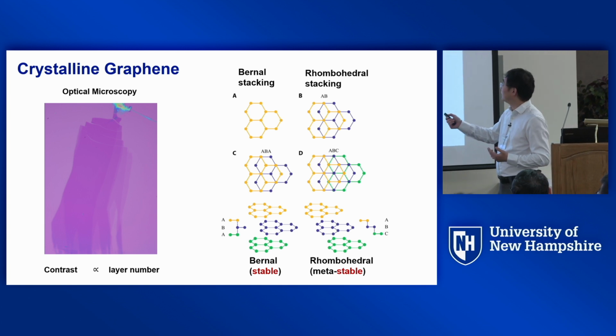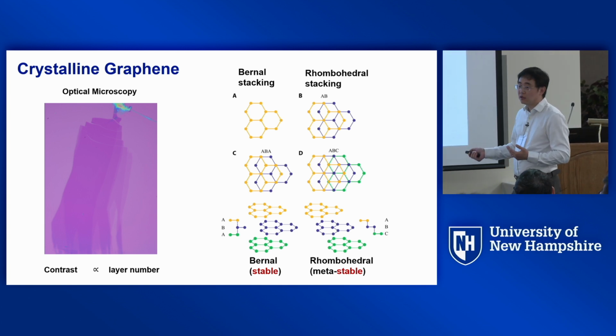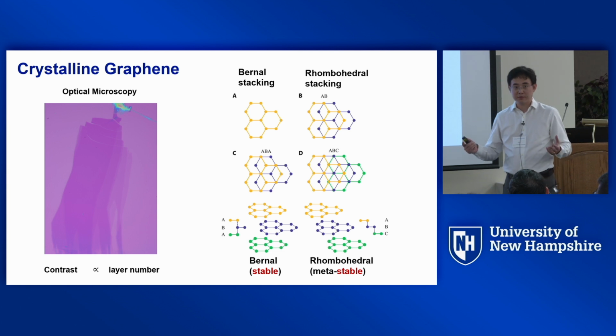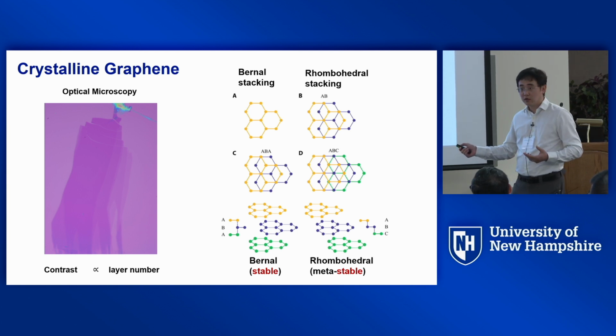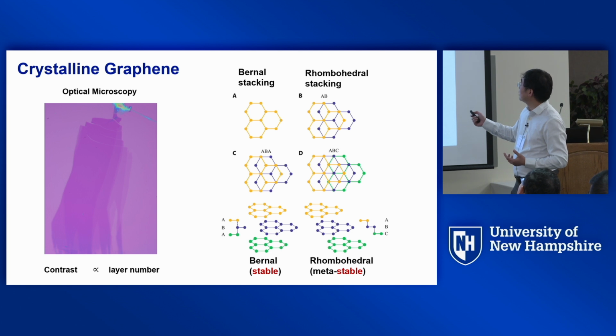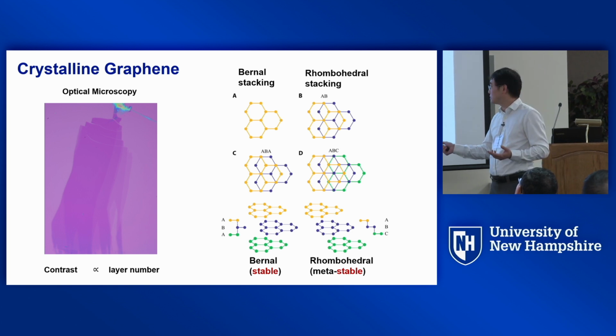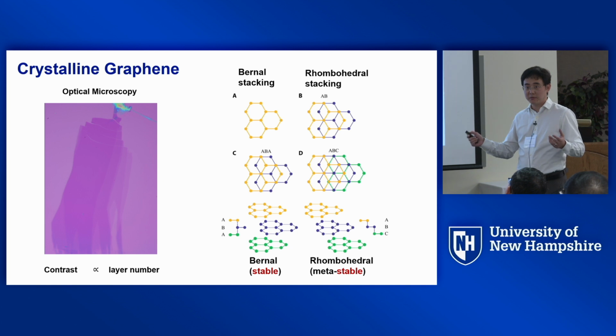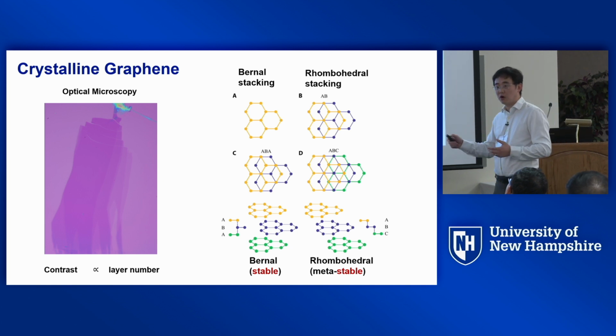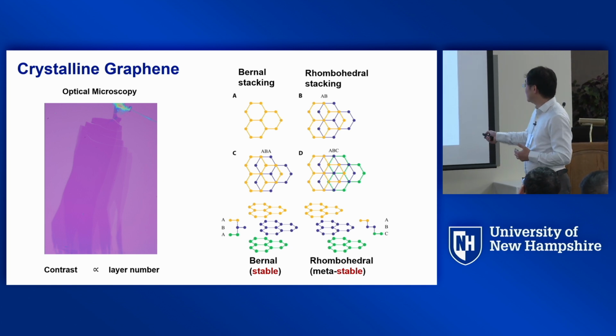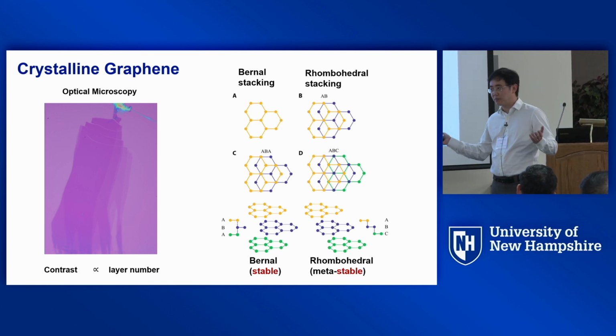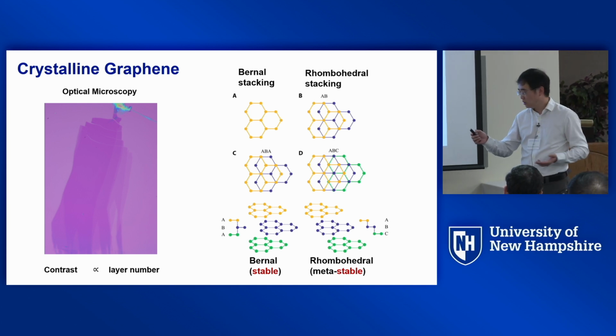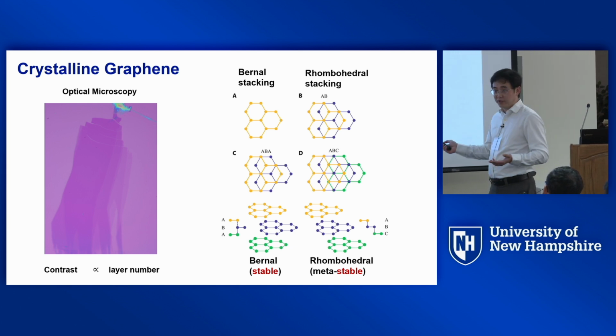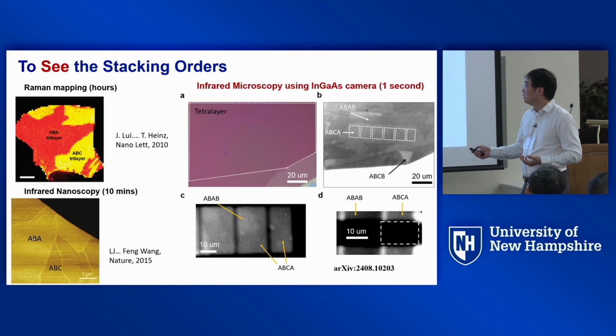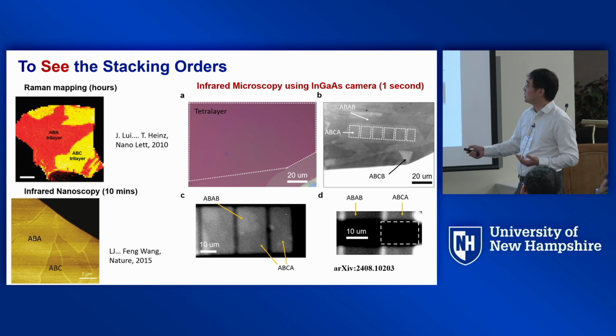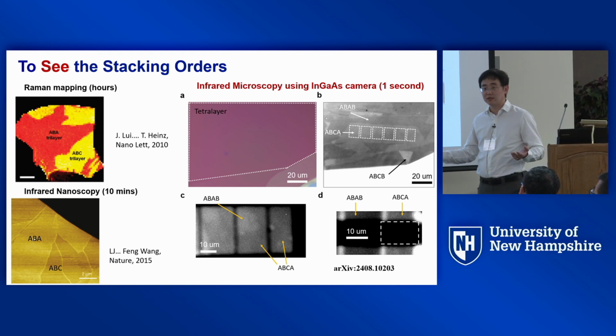One is known as Bernal stacking or ABA stacking. And this is the most stable form of graphite. 80% of graphite is in Bernal stacking. There's another stacking order known as rhombohedral stacking, which is not as stable as Bernal, but it's also a local minimum in energy. It's the second most stable form of graphene layers. It's also known as ABC stacking. It's metastable. Probably 10% of graphite is rhombohedral. Well, this rhombohedral graphene or graphite is actually extremely interesting for flat band and topological physics. First, let me convince you that in experiment we can indeed detect different stacking orders.